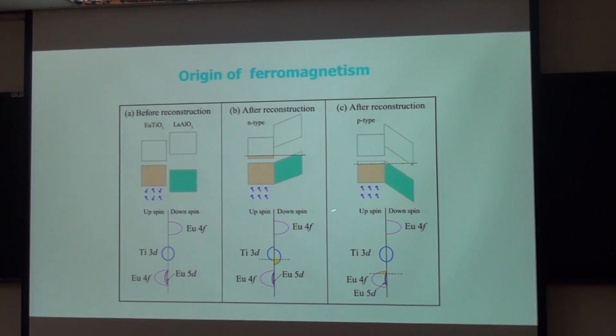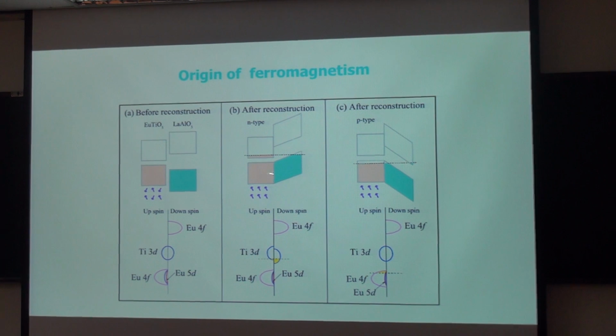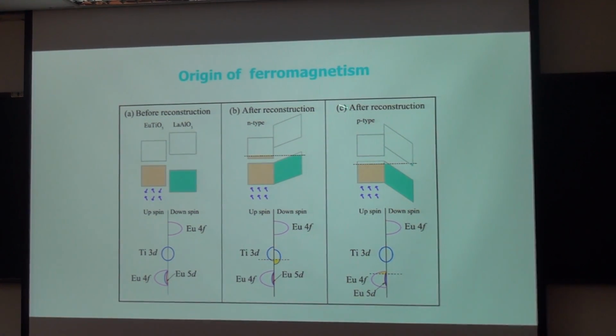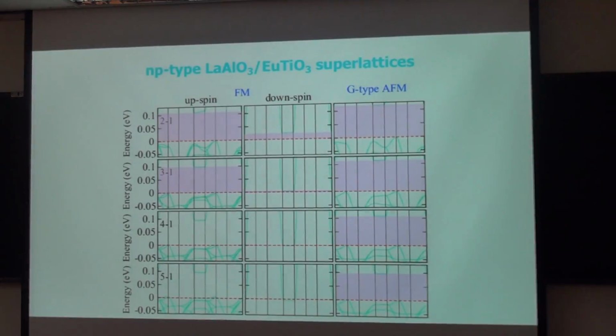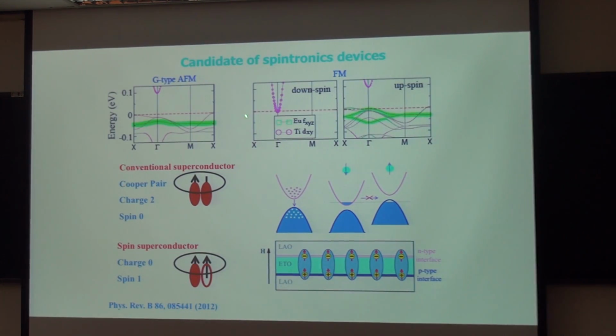This picture shows the emergence of ferromagnetism in this system. The fully antiferromagnetically coupled 4f localized moments become ferromagnetically coupled in both the n-type and p-type superlattices. But an interesting system is the np-type superlattice, where we can find that as the polar layer increases, the band gap, that is the shaded area, diminishes. And we can find in this case, it becomes a semiconductor. But unlike a conventional semiconductor, both the electron pocket and the hole pocket in this case are fully spin polarized.